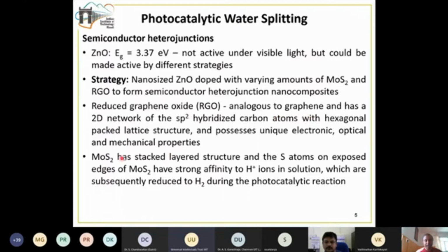Another material which we have used here is MoS2, molybdenum disulfide. It is also a two-dimensional material. It has a stacked layered structure, just like a pile of paper. And the beauty of MoS2 is that it has sulfur atoms on its exposed edges. These sulfur atoms on the exposed edges have a very strong affinity towards the H plus ions in the solution. So they can grab these H plus ions, and eventually these H plus ions can be further reduced to H2 during the photocatalytic reaction. That's the reason we are using MoS2 in this case.